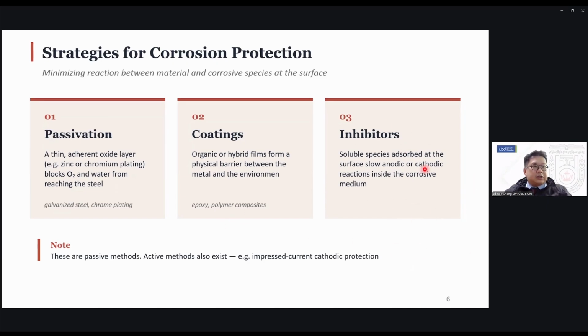And then the last but not least common method is using inhibitors. With this one, you try to add soluble species to the corrosion medium that hopefully will help to block the anodic and cathodic sites. And as I mentioned earlier, you can also introduce a current to maintain a surface potential that's almost the same, so you don't actually have cathodic and anodic areas that might trigger the electrochemical process.